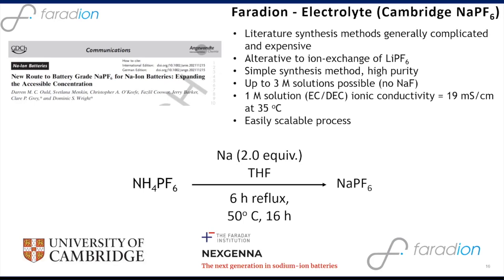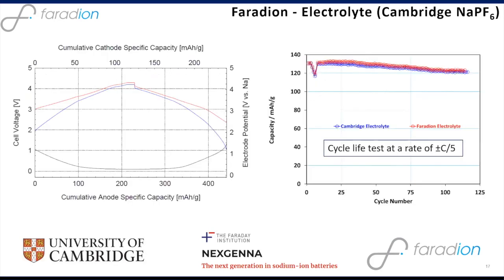So the guys at Cambridge did a great job in developing a new synthesis method by finding a low cost commercially available precursor, ammonium PF6, and then using sodium metal, in this case, two equivalents of sodium metal over the stoichiometric amount, refluxing it in an organic solvent like THF, and having a quantitative delivery of NaPF6 in high purity. So this was a really nice piece of work, and we think this is a scalable process.